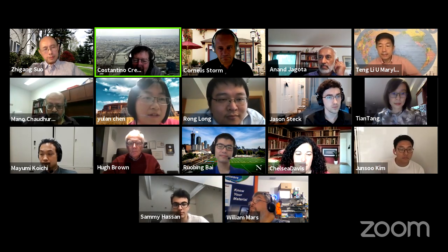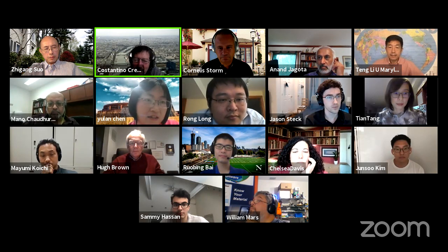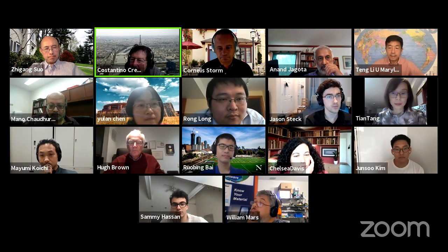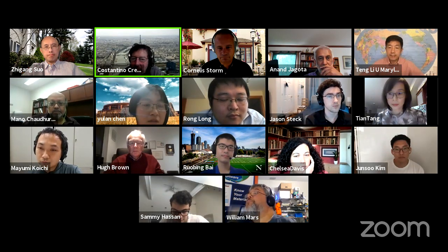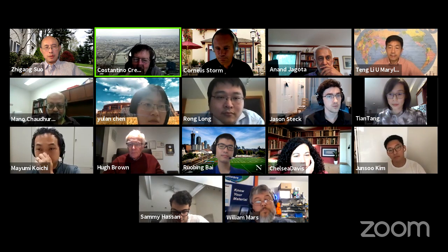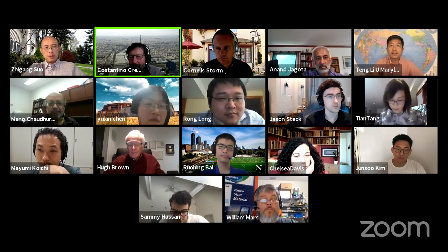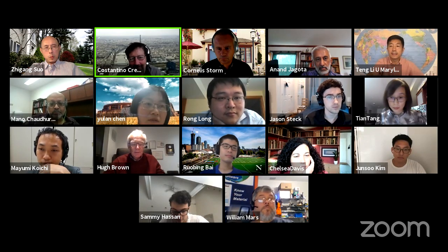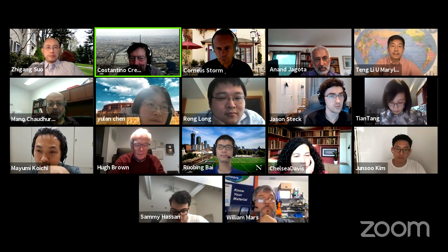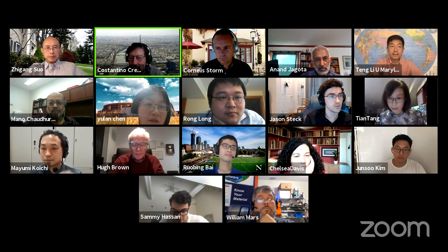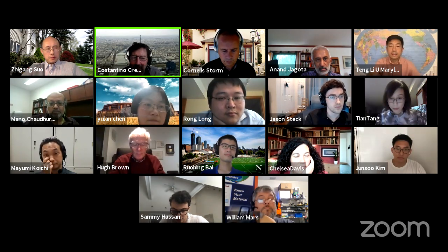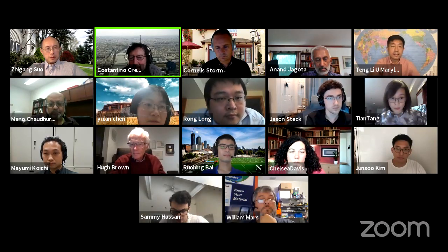Of course, non-transparent would be interesting, or at least not very transparent. So we've played a little bit. You can, to a certain extent, reduce transparency because you don't need to go very deep. If you can go in 50 micron, you can have a nice measurement, at least close to the surface. So I think it's possible. Now, if you really have absorption, like carbon black, that is not the right technique for this kind of thing, or maybe you have to go to other types of radiation. But for example, if you don't completely lose the transparency, I think we have tried some experiments which seem to show that this is doable and interesting.